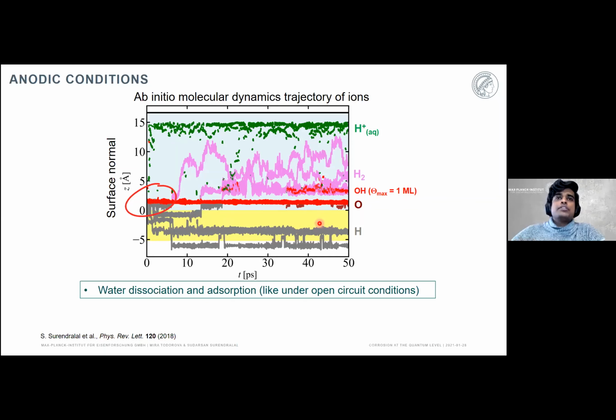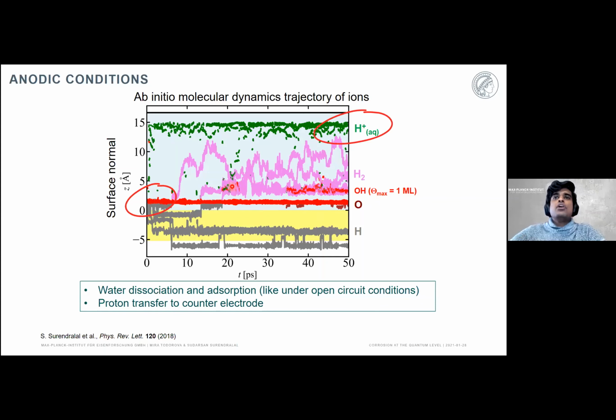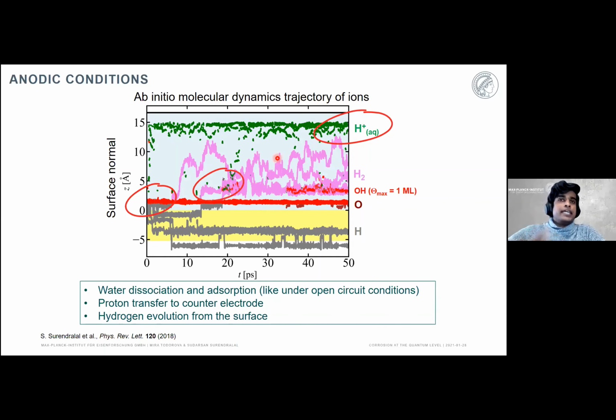We also see two other things. First, we see the proton transfer from the surface of the magnesium to the counter electrode. But this happens due to a Grotthuss mechanism and the applied electric field. So the hydronium ion that is formed in solution would like to migrate to the negatively charged counter electrode. More excitingly for us, what we also see from these simulations, from these violet curves, is the evolution of hydrogen from the surface of the magnesium. This is really what we wanted to see during these simulations.